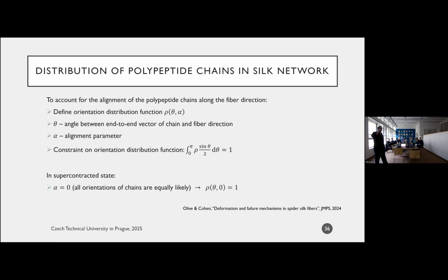And so to model this, we said, let's define a distribution function. We'll call it rho here, and I'll show you the explicit formulation later on, but this is just a general sense. We need an orientation function that relates the angle between a chain and the end-to-end distance, the probability of having a chain with a specific orientation to the fiber direction. And this distribution function also needs to be a function of the process that we're doing. How much did we pre-stretch while we dehydrated? This is the probability density function. We defined it so that if there is no alignment, if it's completely supercontracted, then there's no ordering in the system.